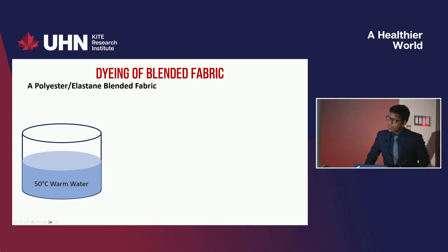The question is why we want to start with warm water. Again, as I said, which material we are dyeing is a big consideration. For instance, polyester and elastane are very hydrophobic. If we start with very low temperature, cold water, the wetting process takes a lot of time. In this case, I'll get the fabric wet within 10 minutes. If I start with cold water, an even wetting will take almost an hour with polyester. So that's why we start with a warm temperature, for instance, here 50 degrees centigrade.